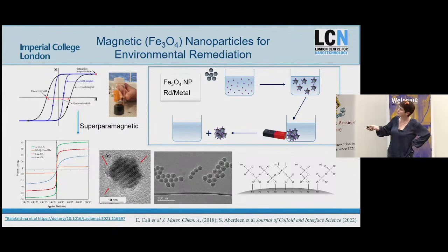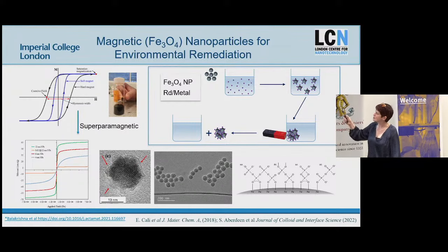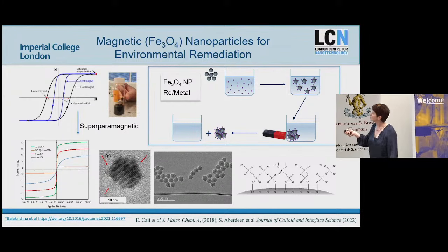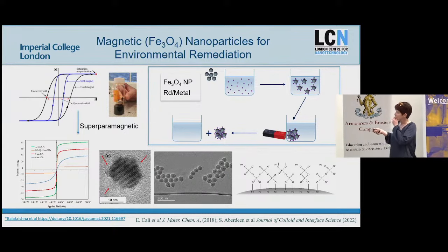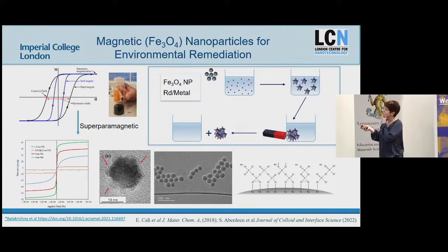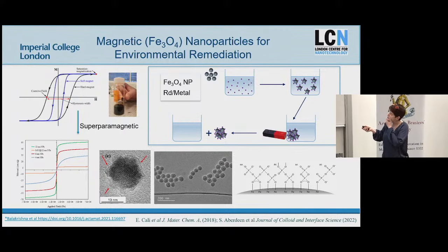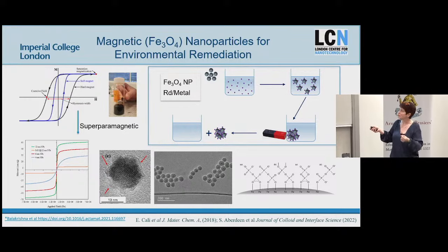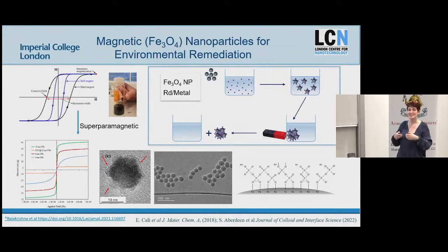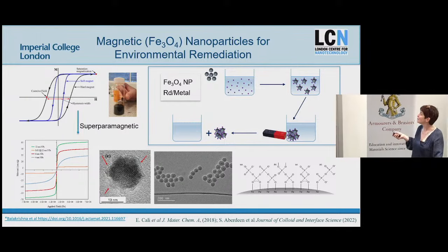So here's a beautiful magnetite nanoparticle. You can see it's beautifully crystalline. We can also coat it with silica if we want to put it in something acidic, and we can create these really uniform monodispersed samples. The magnetization, it turns out, and you might expect, because we're looking at the volume, changes as a function of particle size, so you can control that very, very accurately.